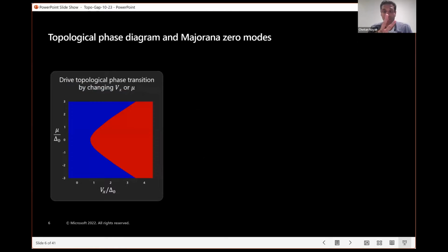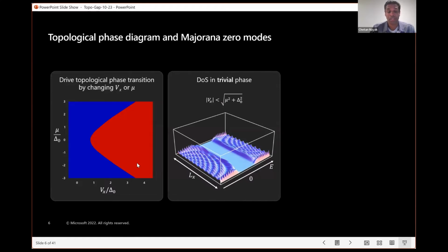Within that simplified model, there are 2 phases. Why is this model so interesting? I said it has a topological phase. I'm going to generally use red for the topological phase and blue for the trivial phase. The topological phase occurs at high field for some range of densities, which translates to chemical potentials. The blue phase occurs at low fields. In the trivial phase, the blue phase, it's a classic BCS density of states, with no states underneath the gap.